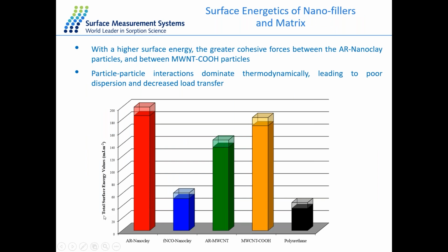So these are the corresponding results. Here we've obtained the total surface energy of each of our samples, and this is the contribution of our dispersive surface energy plus our specific surface energy. What we really want to understand is the effect of the cohesion forces between our materials. With materials with high surface energies, we can assume that they have a higher particle-to-particle interaction. This may lead to aggregation of the sample, which may lead to poor dispersion and poor blending. And in cases with particles that have lower surface energy, this can give rise to better blending of our materials.